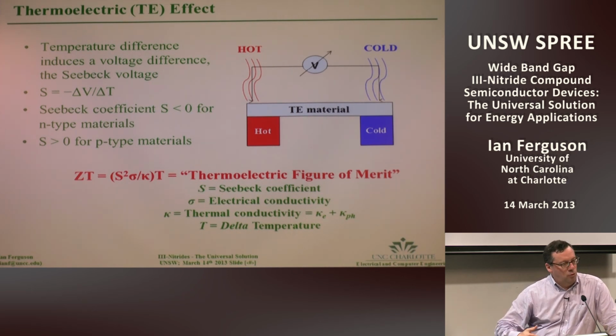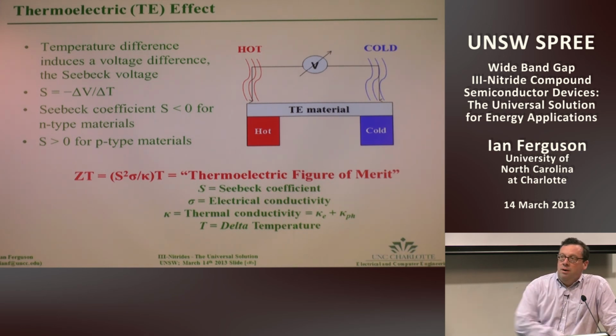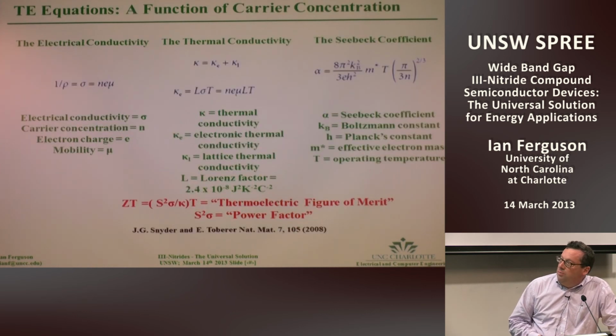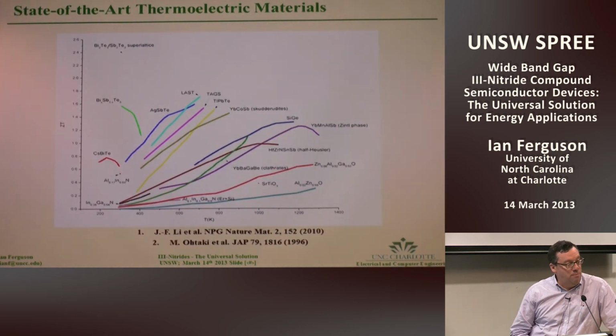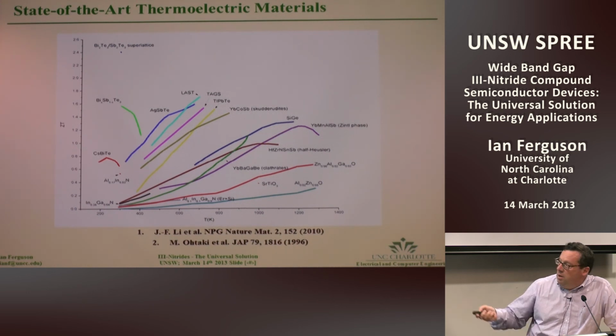scavenging, if you're going towards hybrid concentrated systems, you're going to have localized very high temperatures within the devices, and silicon will stop working at some point. It just won't work well. So our job here was to take the nitrides, which are wide band gap materials and tend to be more robust. Secondly, if you remember about the p-doping, as you increase the temperature of the device, your p-doping should improve because you ionize more centers within it. But you see most of these other materials drop off with temperature.